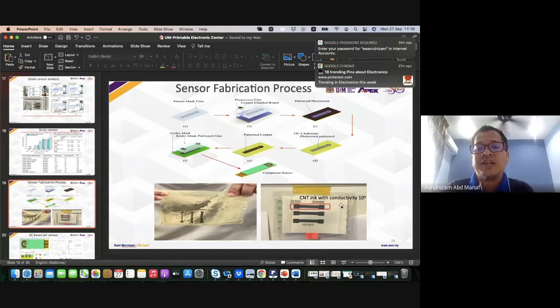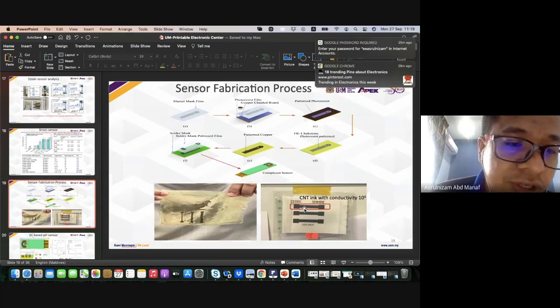So if a single layer can be conductive enough, that's good, because you can lower your cost and simplify the process. But in our experience, we need multiple layers to have good conductivity.